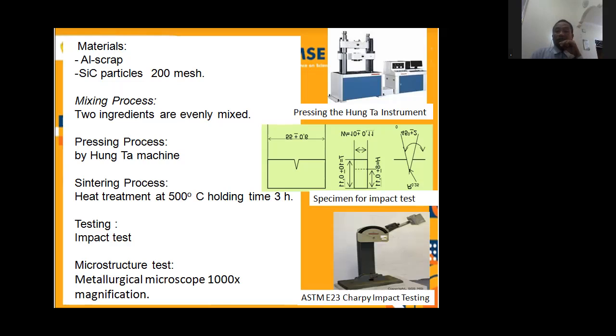This leads to the identification of the structure of the metal by clarifying the grain boundaries of the metal. To observe the microstructure of the specimen after the impact test, the specimen is mounted with resin to facilitate the polishing process. After that, the surface was rubbed with a velvet cloth with the addition of a sufficient amount of autosol. So that is the preparation beforehand for the microstructure testing.